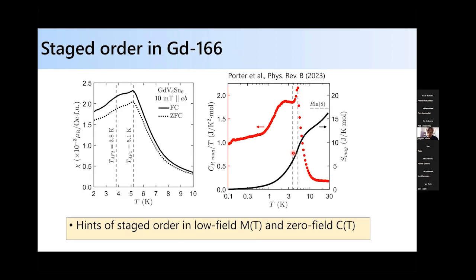So to do that, I'm going to show you some resonant X-ray scattering data exploring that. But digging in a bit more, if you zoom in on the low temperature susceptibility as a function of temperature, you can see there are two features, something around 5 Kelvin and something a little below 4 Kelvin, in both the susceptibility and potentially in the heat capacity, hinting that there's maybe some staging of the order from these two probes.